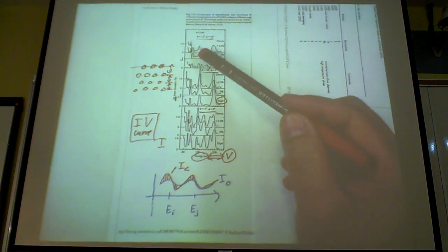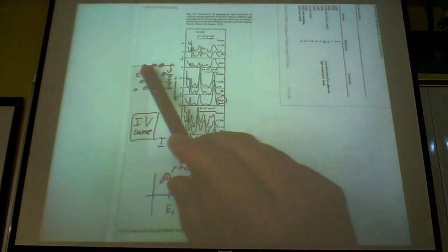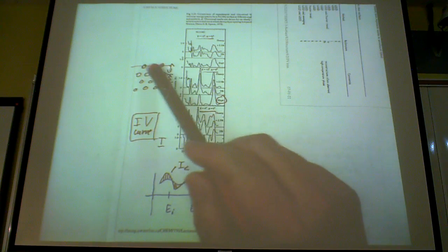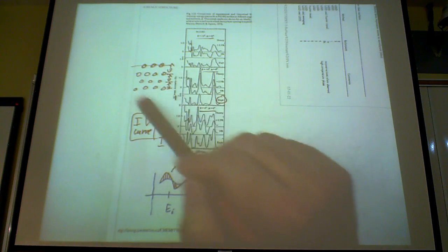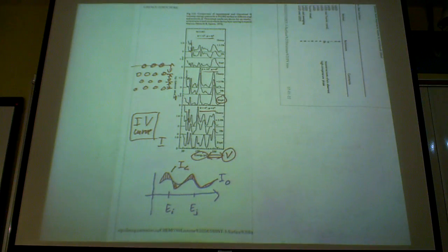This is a cross-section of my selvedge for the 100 direction, okay? And when I say model, what does that mean? It means that I know the position of each of these atoms in real space. I generate a physical model of this, all right? And this is my starting point. So I assume a physical structure for this, and then I do some fancy thing.